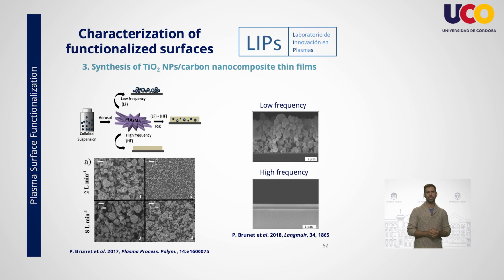On the right, we can see the effect of changing the DBD frequency. By using low frequency, we obtain clusters of nanoparticles like the ones mentioned just before. However, when we switch to a high DBD frequency, instead of nanoparticles, a thin film coating is obtained. In these images, instead of a frontal view, we are looking at a cross-section obtained after a transversal cut of the sample. Thus, in a simple way, we can not only see the morphology of the sample, but also the thickness of the layer of the deposited material.